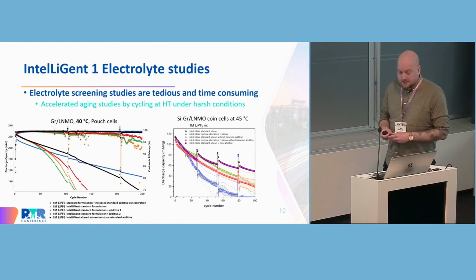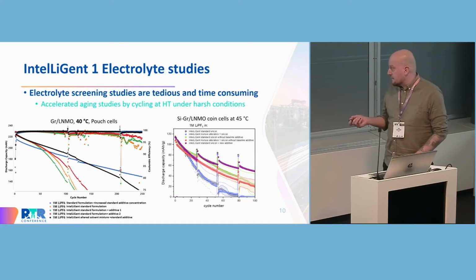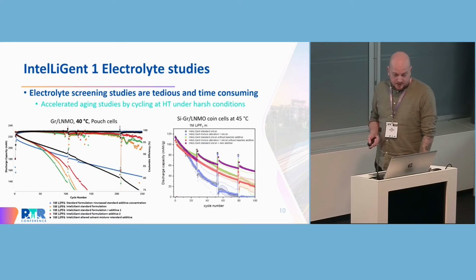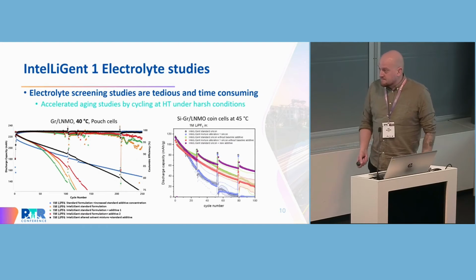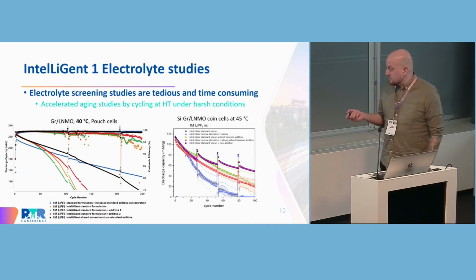And they were also cycled at high temperature, which is even more challenging for silicon-based materials. And in black and blue, you see our baselines, which were terrible. They basically died right away.